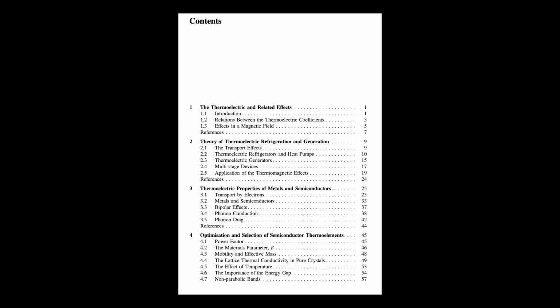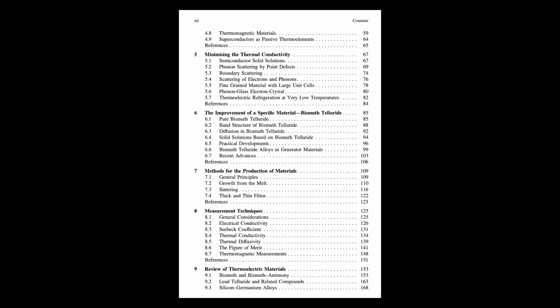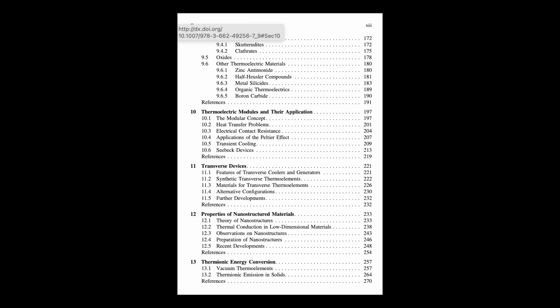The outline then highlights the energy gap, Eg. Why do we need to worry about that? The energy gap, Eg, is that forbidden energy zone in semiconductors. It's vital for preventing mixed conduction. That's when both electrons and holes are carrying significant current. If that happens, their Seebeck coefficients, one usually negative, one positive, tend to partly cancel each other out. Bad for the overall alpha, bad for ZT. So to avoid this at your operating temperature, the gap needs to be big enough, rule of thumb, at least 6 times kT, the thermal energy, keeps one carrier type dominant.